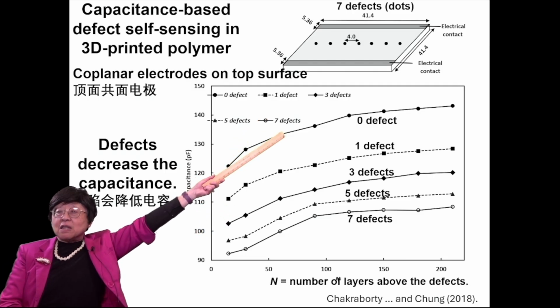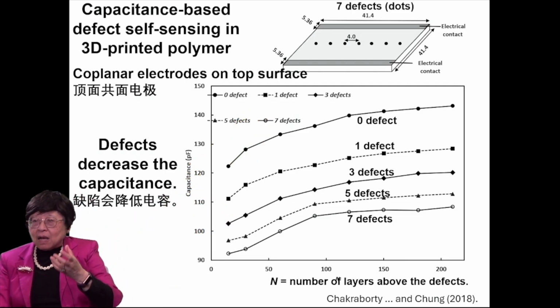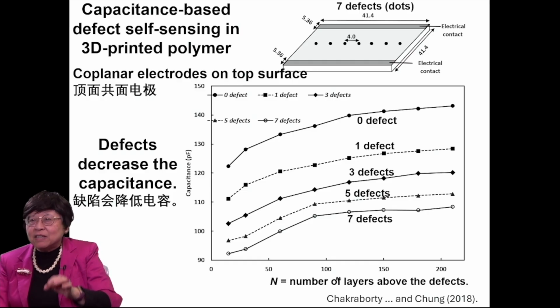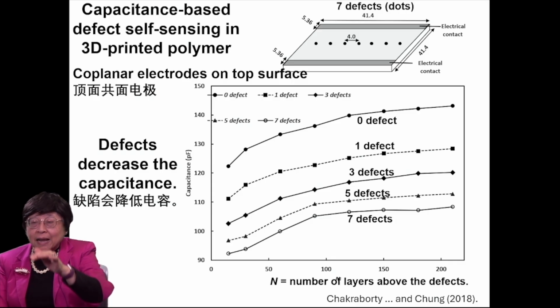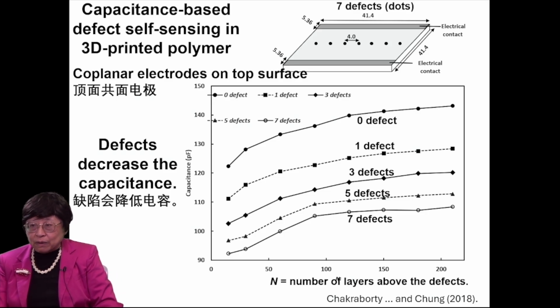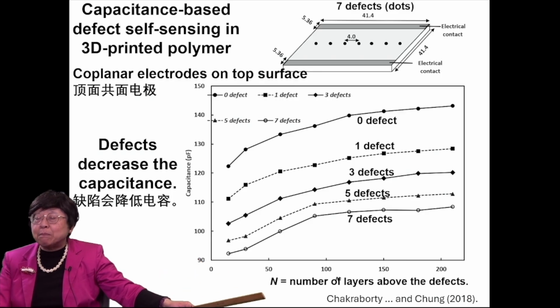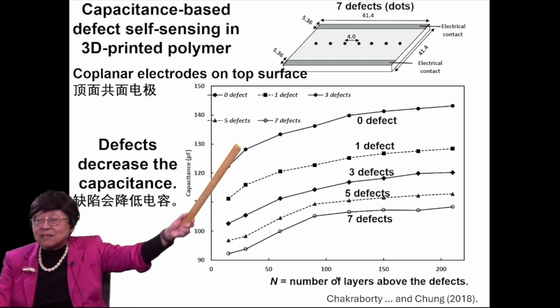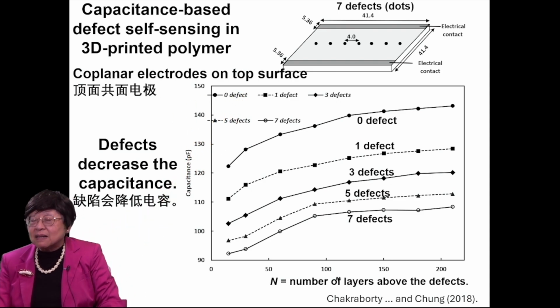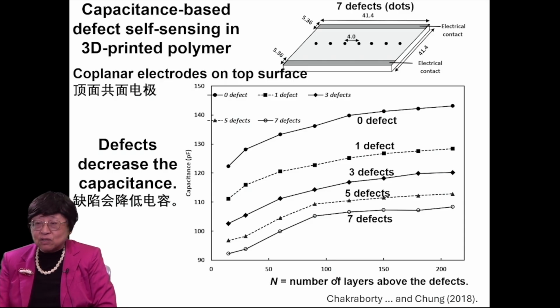We artificially positioned these dots, which are artificial damage that occur at certain layers below the top layer. And we control where these defects occur. N is the number of layers above the defects. And we measure the capacitance using these two strips of electrical contacts. And as you have more defects, the capacitance goes down because the electric field is hampered by the presence of the defects. So the capacitance goes down the more defects you have.